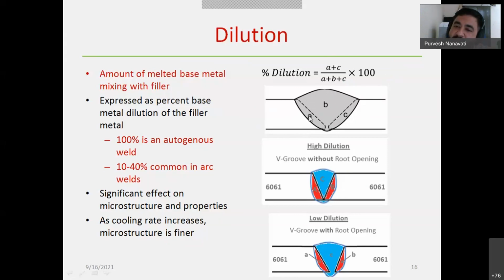Because during welding, what will happen? The melting surface edges will also contribute into the weld metal. So they contribute according to the process and the heat input, right? So if you are not performing welding with filler metal, then it will be an autogenous weld. So in an autogenous weld, dilution is 100%. It means only base metals are contributing into the weld metal, right? Simply speaking, only base metal makes the weld. But if you are going for a non-autogenous process using a consumable, then your base metal will contribute to some extent depending on the arc energy and heat input, right?